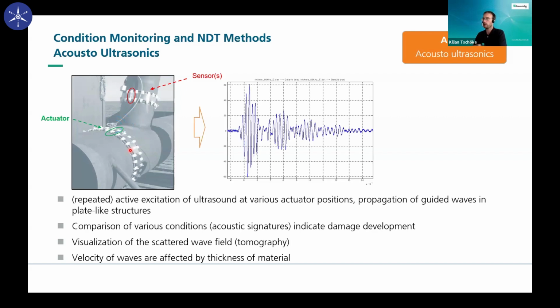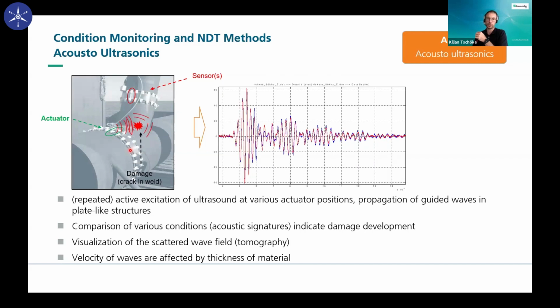Let's say this is the blue curves stored into a database. If you repeat this measurement, if you actively start this measurement again later, 1 day later, 1 week later, 1 year later, and in the time between the measurements there was a damage, then again the wave propagates coming from the transducers, but then you will get reflections or a scattering of your wave coming from this damage, and this will change the received signals.